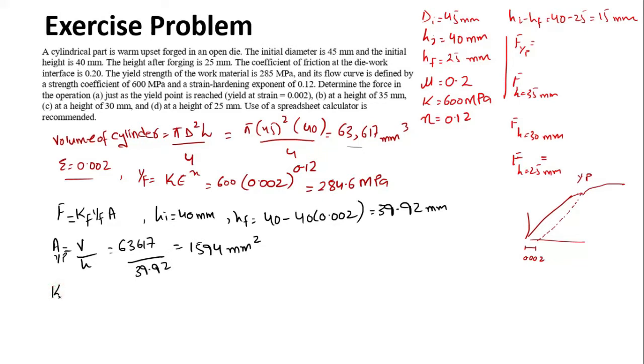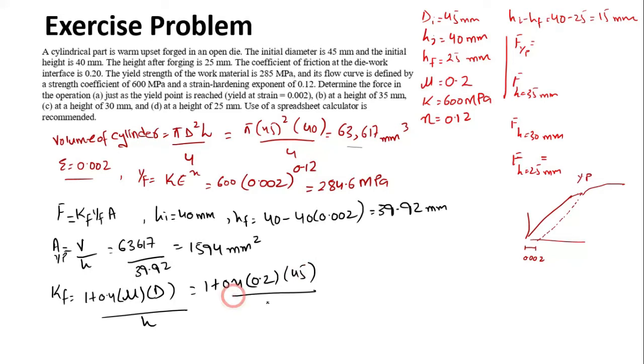Now find out the value of the shape factor, that is 1 plus 0.4 into mu into diameter divided by height. So that would be 1 plus 0.4 into 0.2 into the initial diameter 45 divided by the height at that point, 39.92. So you'll have the value of the shape factor equal to 1.09.